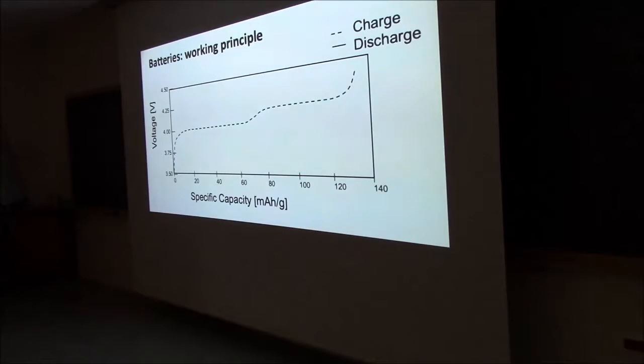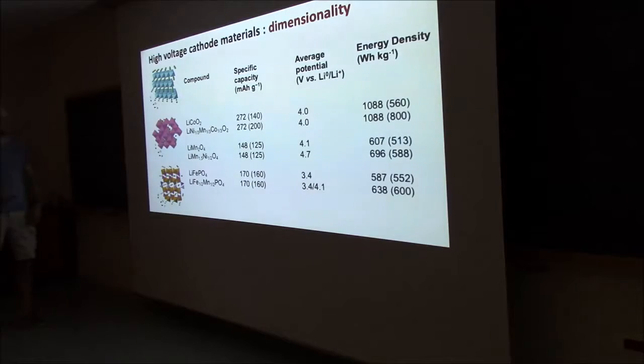the spinel. The fact that there are 2 plateaus means that at 2 different voltages, lithium moves into your structure. In the charging, it moves out, and discharging moves in, but there are 2 different locations where lithium can sit. And first you fill up one, and then you do the next. And if you discharge it, you take it out from one location, the other location, and then you stop. So for lithium cobalt oxide, it's only one plateau, because the lithium is always in similar positions. So these are the 3 materials I was discussing.